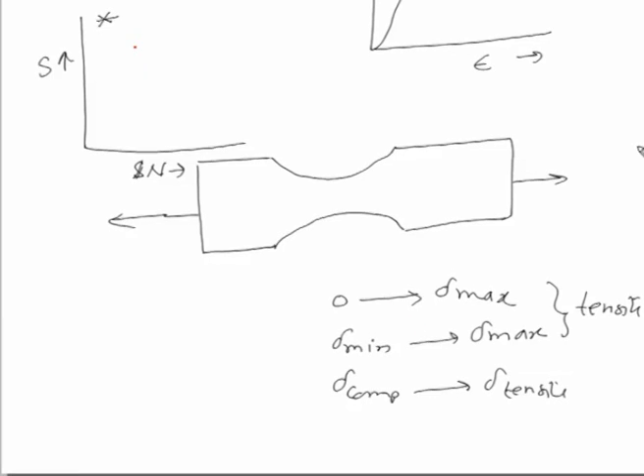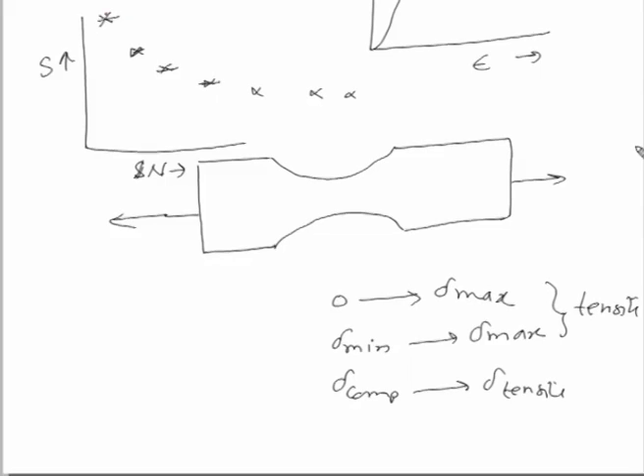Thereafter, we will be conducting the test at 0.8 times the yield stress, which will take somewhat longer, and this is how we will keep on reducing: 0.7 times the yield strength as the maximum stress, then 0.6 times the yield stress, and this is how we keep on doing it. We will find that after reaching somewhere in the band of 0.4 to 0.5 times the yield stress, the number of load cycles, in the case of ferrous metals, becomes the endurance limit.